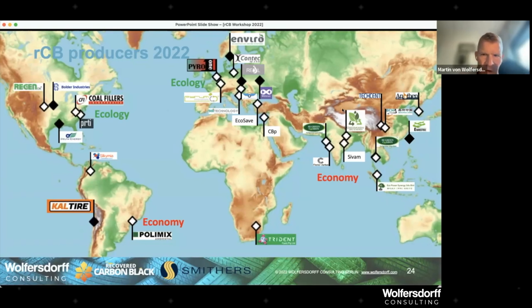Frederick is asking, what is the typical valorization of py oil resulting from rubber pyrolysis presented as RCB co-product, even if it's the major product? You know, typical mass balance would be some 40% recovered carbon black, 50% oil. So they're really co-products, and not one is much bigger than the other. You could argue that recovered carbon black has a higher value, clearly over €1,000 per ton, which we'll see in a moment. And the oil, maybe not 1,000, unless it's a very specific oil, like a Circtec oil, which is really very high quality, post-treated.